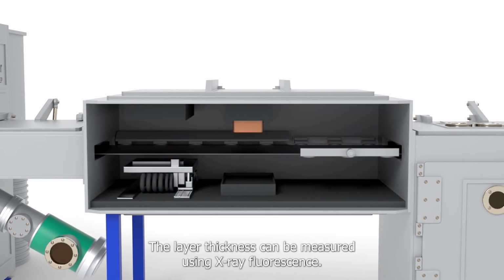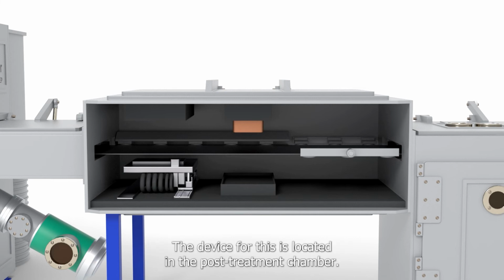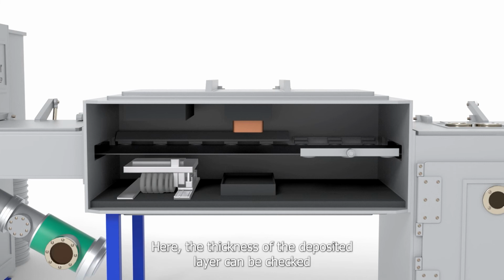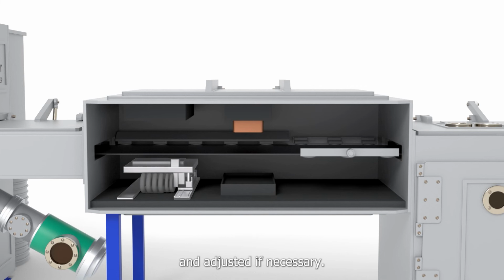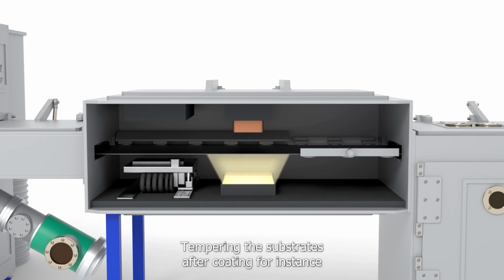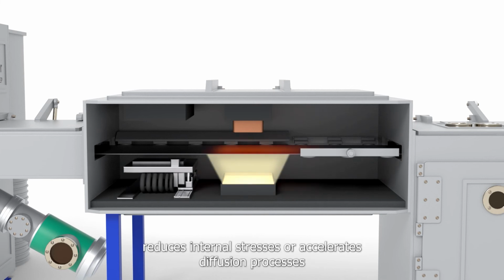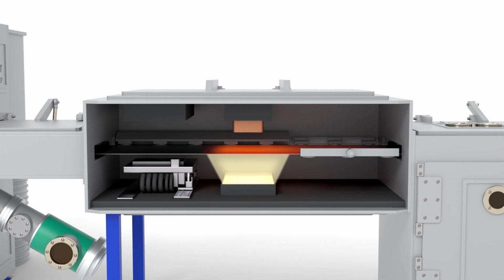Post-treatment. The layer thickness can be measured using X-ray fluorescence. The device for this is located in the post-treatment chamber. Here, the thickness of the deposited layer can be checked and adjusted if necessary. Tempering the substrates after coating, for instance, reduces internal stresses or accelerates diffusion processes within the layer or between substrate and layer.